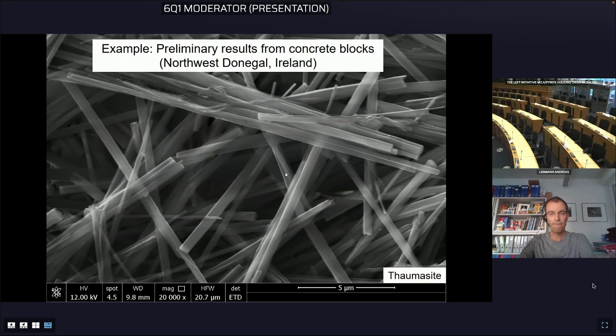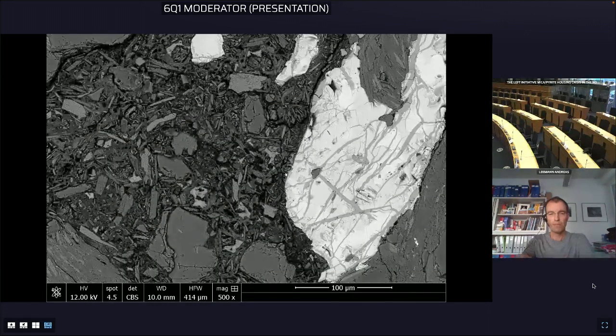Next, please. Okay, this is a polished concrete section. You see the scale as well. The grayscale values more or less represent the density of the phases you have here. Standing out, very bright, this is pyrrhotite. What you can observe as well in this bright mineral are veins that are somewhat darker. This is oxidized pyrrhotite. To your left-hand side is more or less the cement paste. Now, I did a sulfur mapping of this, showing where the sulfur at this particular location is.